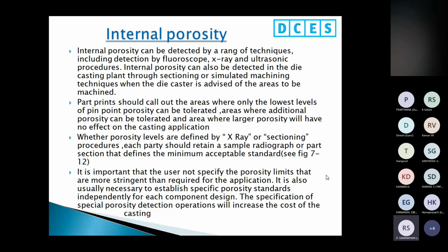Internal porosity. Internal porosity can be detected by a range of techniques, including detection by fluoroscope, X-ray, and ultrasonic procedure. Internal porosity can also be detected in the die casting plant through sectioning and simulated machining techniques, when the die caster is advised of the areas to be machined. This we usually do in all die casting plants by cutting the component.